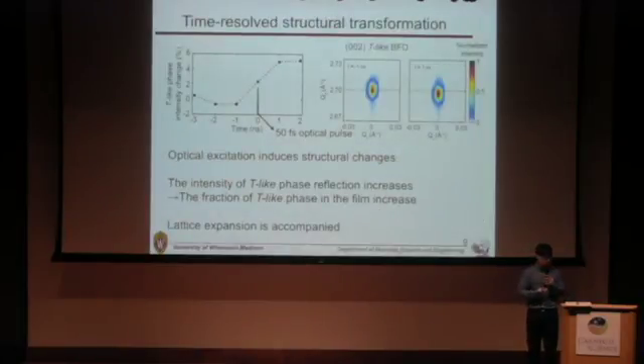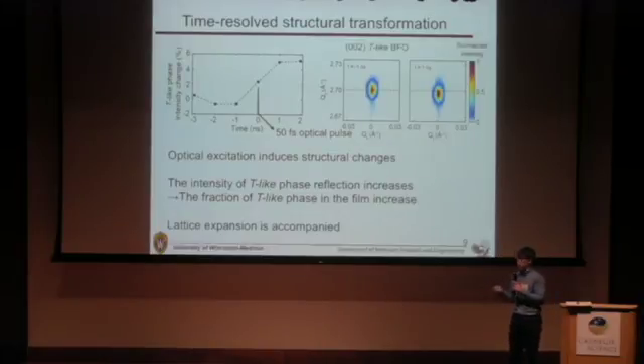Here's the first result of our experiment. So it is a time-resolved structural transformation. Since the T-like phase reflection intensity and also the R-like phase reflection intensity are proportional to the fraction of the phases in the system, we can use the T-like phase intensity changes as a signal of the phase transition. So we plot here the T-like phase intensity changes as a function of time. Time 0 means the time when the 50 femtosecond optical pulse is induced, and we see the saturation of the intensity at 1 nanosecond. Also, the reflection shifted to lower wave vector, indicating lattice expansion.